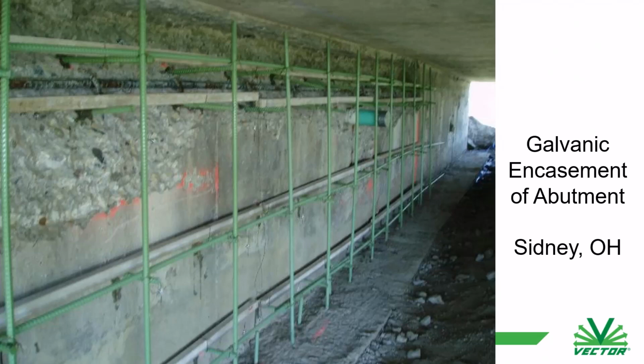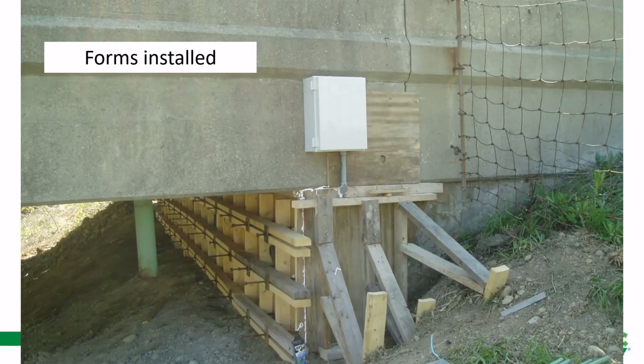And then in the case in Ohio, they like the epoxy coated bar, so they used epoxy coated bar in the facing. A lot of places will just use black bar, and we'll just tie the black bar in with the galvanic system, so the black bar is also being protected by the galvanic anodes. And then you have the forms installed. This was an early use of self-compacting concrete to do a form and pour repair.